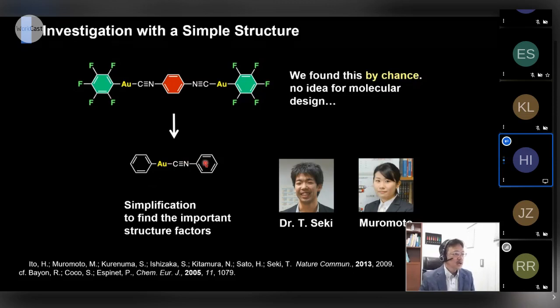So this compound was found completely by chance. For the first time, we tried to find a catalyst, not a photocatalyst, just a transition metal catalyst. We tried to find a catalyst using this structure, but we did not find any catalytic activity. This is a very, very stable compound that cannot show any catalytic activity. Instead of catalytic activity, we found a very fantastic mechanochromic luminescence property. So at first, we had no idea why this compound shows mechanochromic luminescence properties.